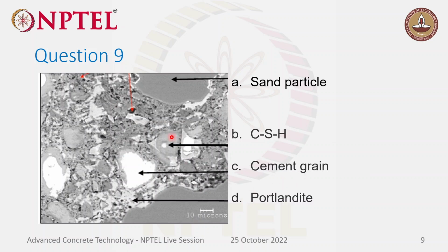So the first part doesn't have any gradients, which means it's a sand particle. It does not have any gradation and it's larger in size also. And coming to option B, B is nothing but CSH because the outer part is hydrated and the inner part still remains as unhydrated cement grain. And unhydrated cement grain appears very bright in the backscatter electron image compared to CSH. And Portlandite also appears in bright phases, but since it's mixed with the ground mass, it will be mixed with the gray phases, but it will be a bright spot.